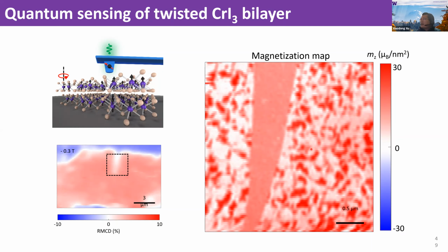Then in this twisted bilayer regime, you see there's a red area which shows ferromagnet, and the white is antiferromagnet. Basically, you see these very disordered-looking patterns, right? It's nothing like a Moiré magnet, just a very disordered pattern, but it is indeed a mixture of a ferromagnet and an antiferromagnet.